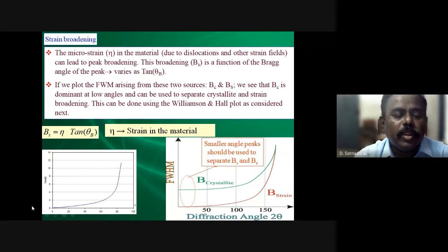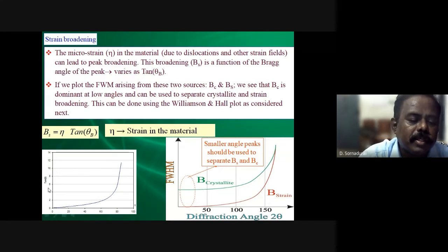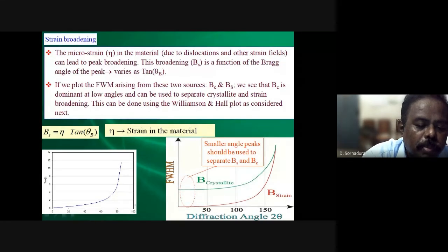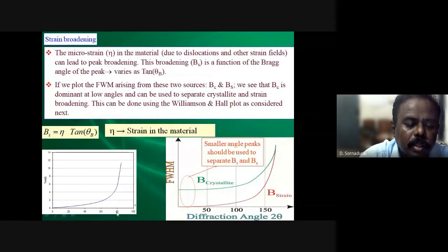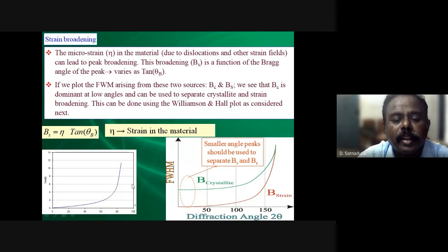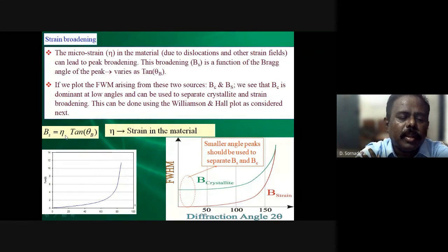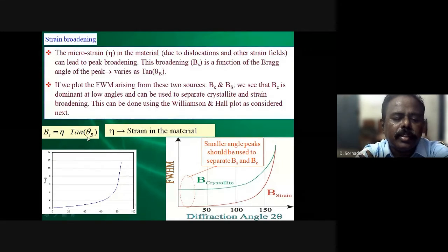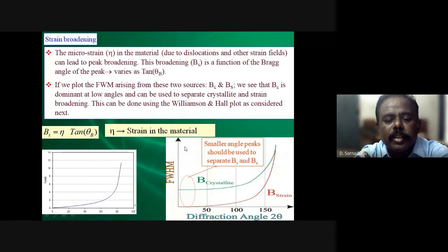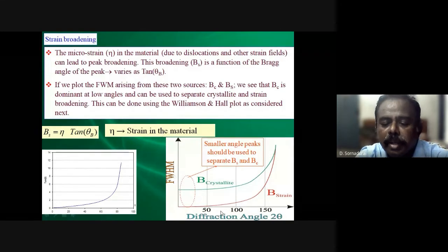For that, for example, this curve is tan theta plotted against 2 theta. You can see that it is increasing like this. Suddenly above 80 it is going up like anything. From this you can find the strain broadening, beta s, because of the tan function like this, and that is the strain in the material. Similarly, this is the crystallite.